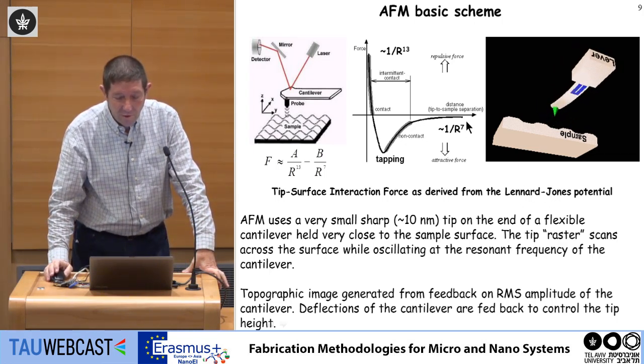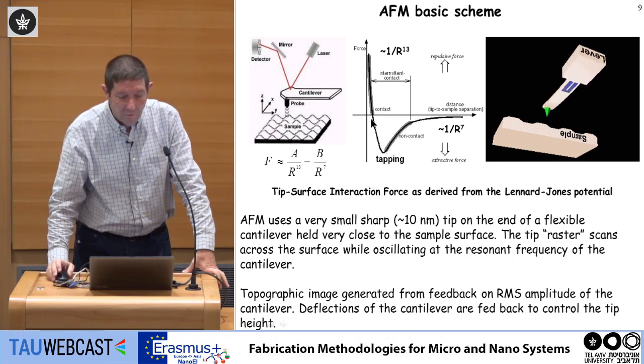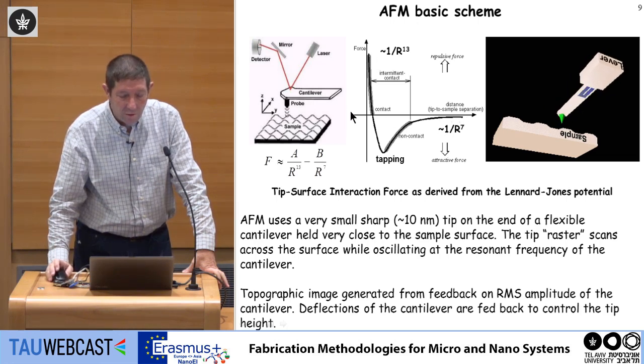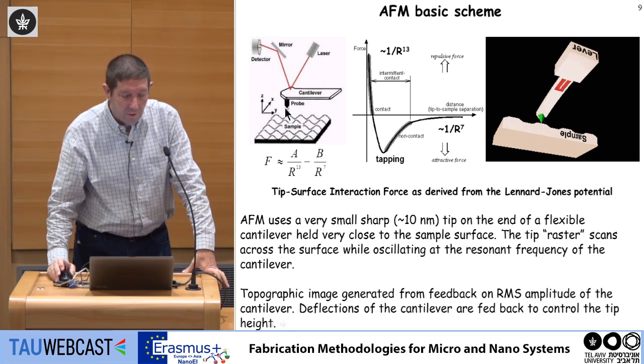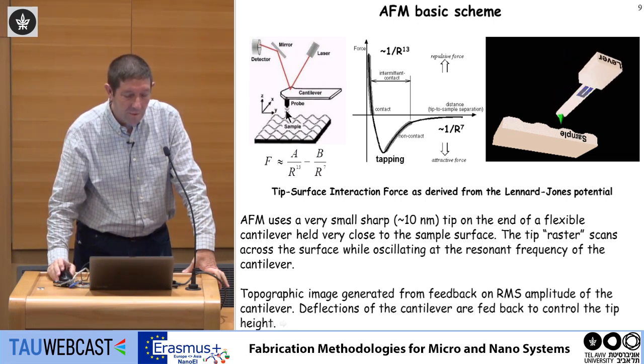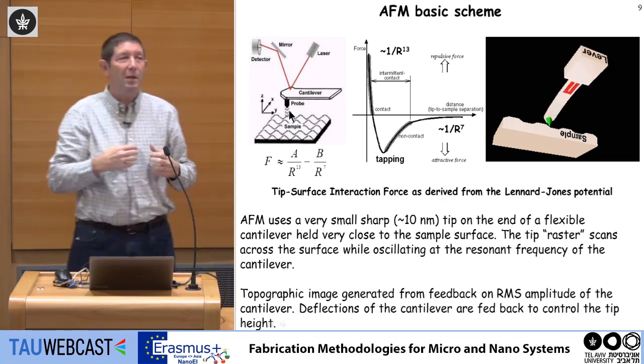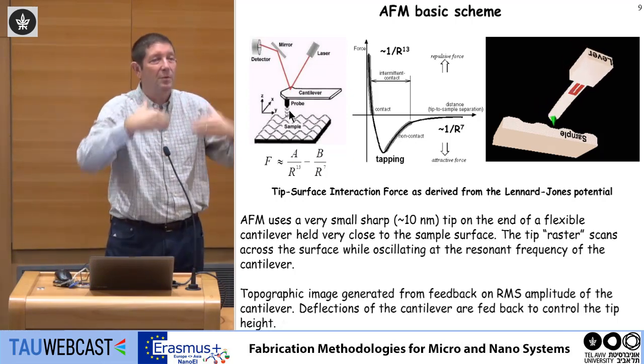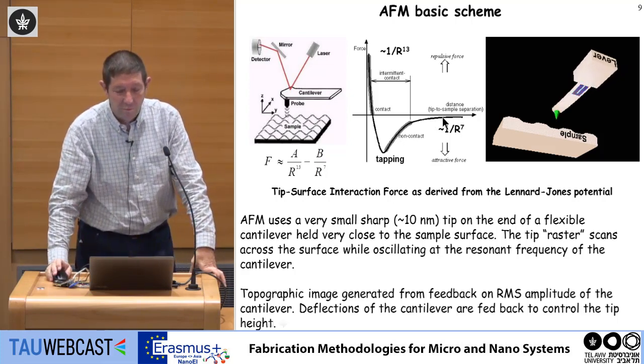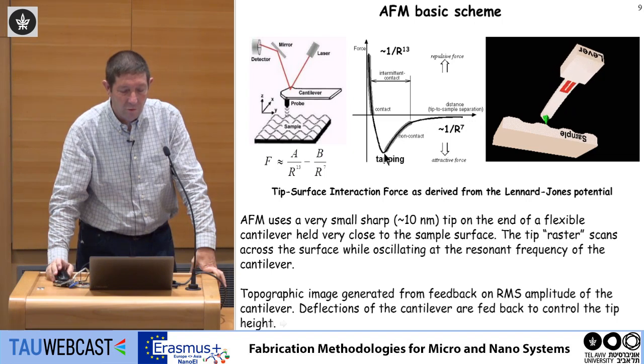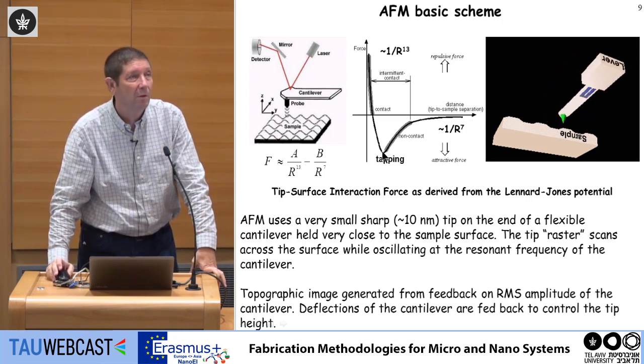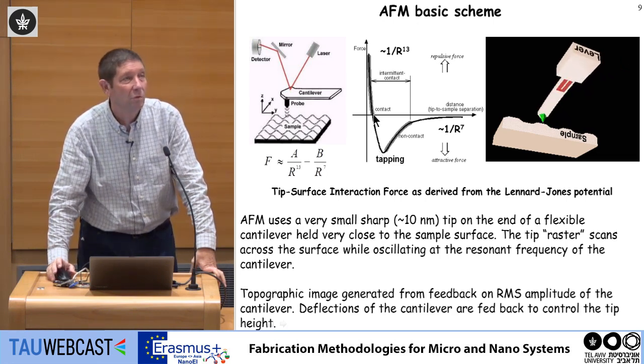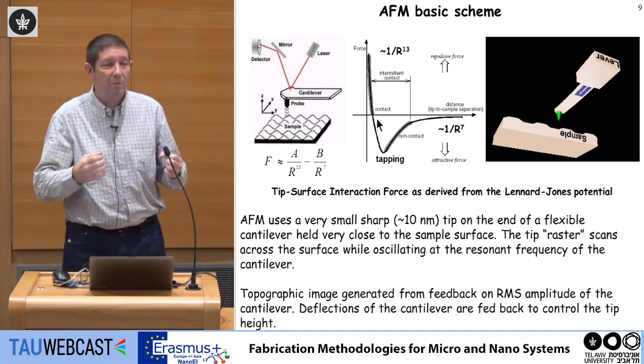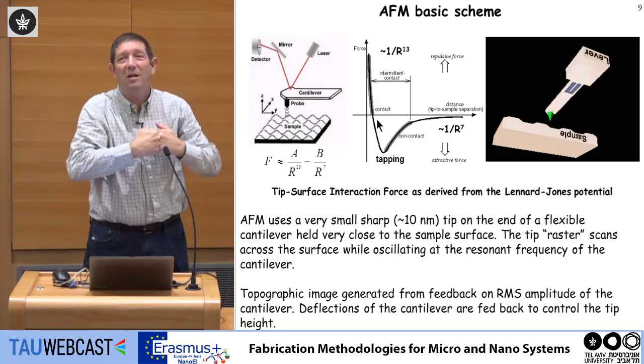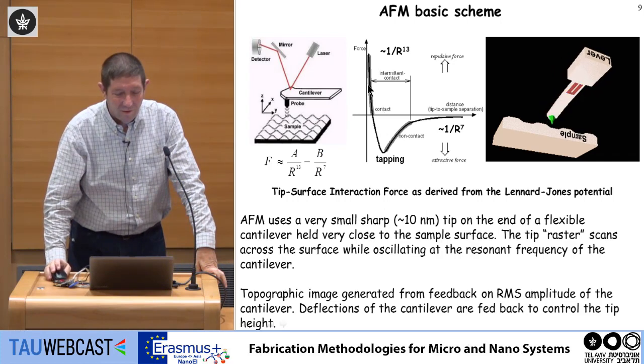Lennard-Jones potential, that you say that initially, as you're getting closer, you may have some attraction forces. And if you're getting too close, so this is the potential. If you take one metal, material A, and move it closer to the surface, material B, you may have some overlap of electronic orbitals or van der Waals forces, and you can have some attraction between the two materials. So initially, at infinity, the potential is 0. As you're getting closer, in many situations, the energy is lower. But as you're getting too close, then the potential starts to go in the opposite direction, which means the two materials kind of hit each other, and there are strong repulsion forces.